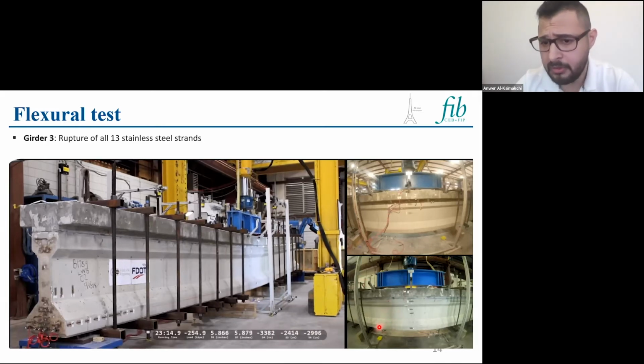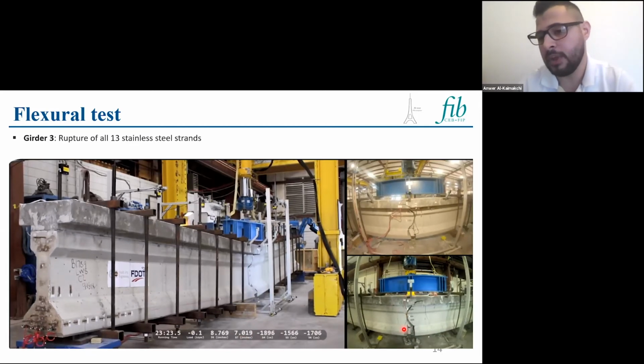The girder exhibited many flexural cracks before failure, and the deflection was large. We had deflection of almost 6 inches here, and then it failed. We saw it failed due to rupture of all stainless steel strands because of their low ductility. It failed while the concrete in the compression zone was still intact, but it gave us a good warning, where many flexural cracks formed.